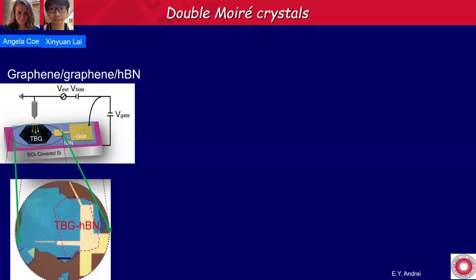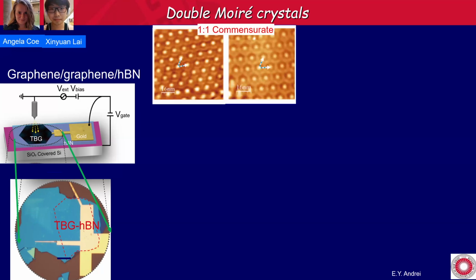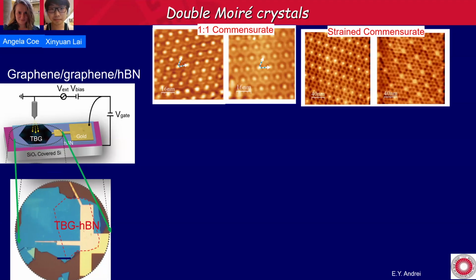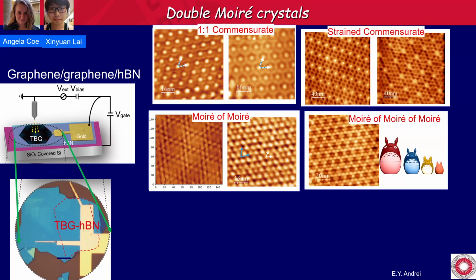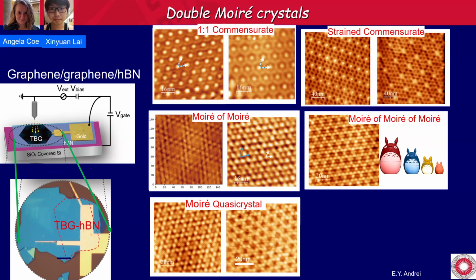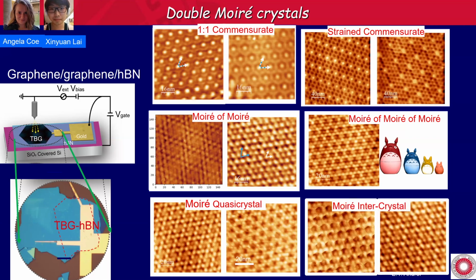Okay, so this is the experiment. We had twisted bilayer graphene on boron nitride. We did our best to try to align it, and then we expected to see something. What the transport people have seen, aligning boron nitride to twisted bilayer graphene, and indeed we have a sample here that is commensurate. Okay, 1-to-1 commensurate, exactly what they were supposed to have seen. But then we go to a different region of the sample. It looks totally different. It's strain commensurate. Moire of moire. Moire of moire of moire. Moire quasicrystal. Moiré inter-crystal. I'm going to explain in a moment what that means.